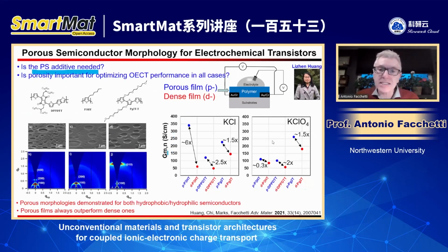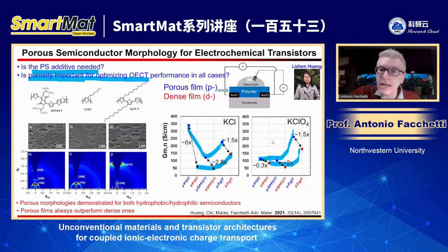The answer is yes. These are the currents for different devices. Black is the transconductance for the dense film, in red here down. And the blue is for the porous. And you see here that no matter if you are using different polymers or different electrolyte, in all cases, the blue is on top of the black, of the red. So it means porosity is also very good to enhance ion penetration and enhance the current in these devices.